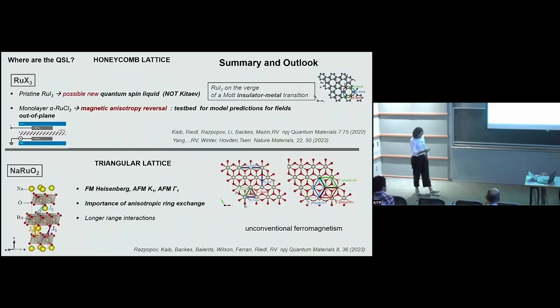My time is over. I just wanted to mention 2 issues: it's very interesting to study these materials, to manipulate them by applying strain of different types. This is maybe a new type of quantum spin liquid. And in the sodium ruthenium oxide, the importance of the anisotropic ring exchange brings a new type of interaction in the system. And we don't have an answer to the disordering effect, but definitely what we can show is that ferromagnetism is important and can explain some experiments. And I thank you for your attention.